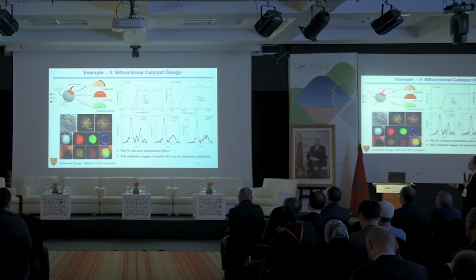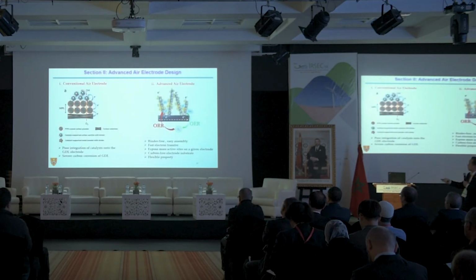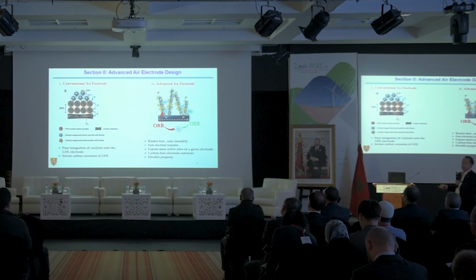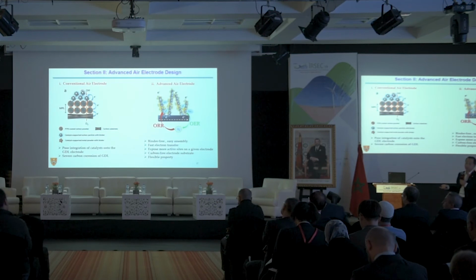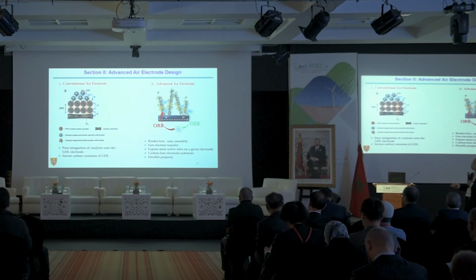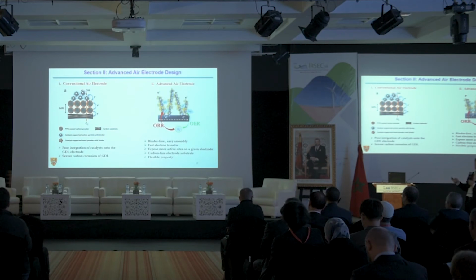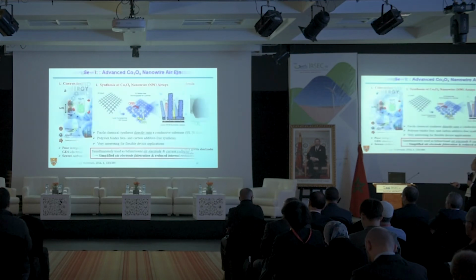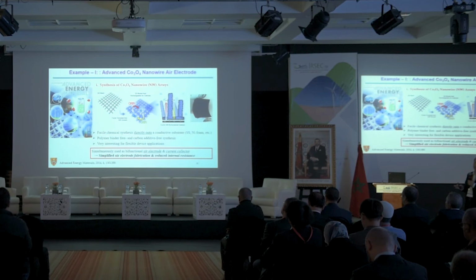Another way we design the catalyst, I would introduce, is air electrode design. As we know, the traditional catalyst is particles, which means we have to coat the catalyst with binder or conductive polymer, then coat it onto the current collector or gas diffusion layer. However, we think this may not be the best way. Another good way we are trying is to grow the catalyst directly onto the substrate, the current collector. One methodology we're using is metal mesh directly, and then you grow cobalt oxide nanowire directly onto the metal mesh. Then you can use this as an electrode directly.